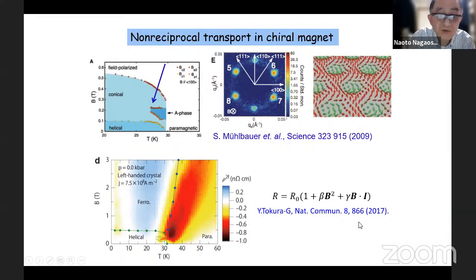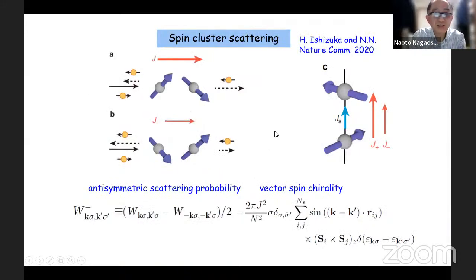So we consider this problem again from the noncollinear spin structure. The problem is that once you have multiple spins, they will scatter the conduction electrons. So what is the effect of the spin-spin correlation? Then we calculate the anti-symmetric probability of conduction electron scattering. That is defined by this expression, W minus, and consequently we observed this S cross S corresponds to the non-reciprocal scattering of the conduction electrons.